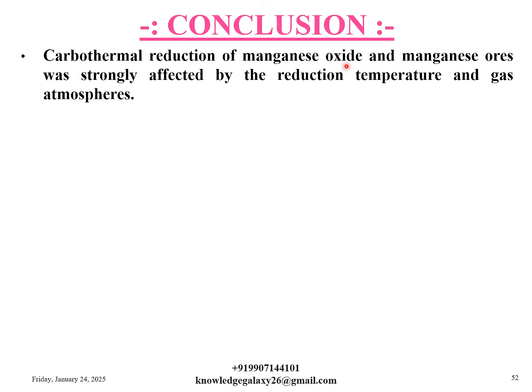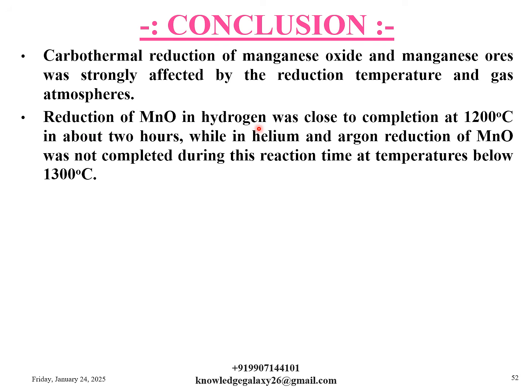So now we have reached the conclusions, and now it's the time to sum up whatever I have described in this presentation. Carbothermal reduction of manganese oxide and manganese ores was strongly affected by the reduction temperature and gas atmospheres. Reduction of MnO in hydrogen was close to completion at 1200 degrees Celsius in about 2 hours, while in helium and argon, reduction of MnO was not completed during this reaction time at temperatures below 1300 degrees Celsius.